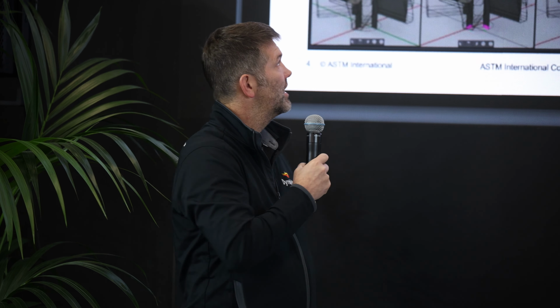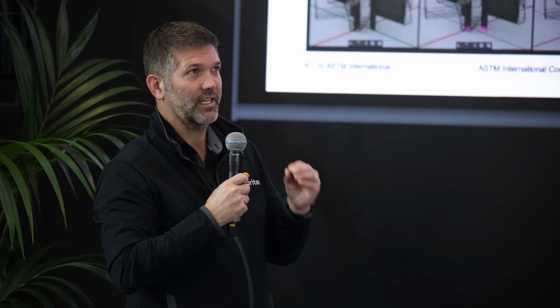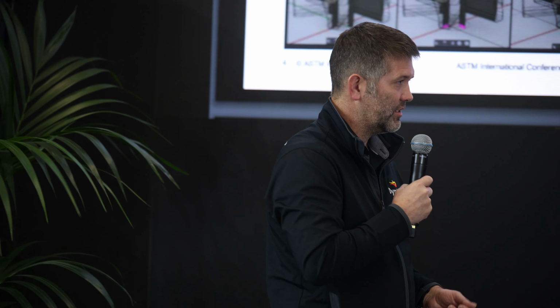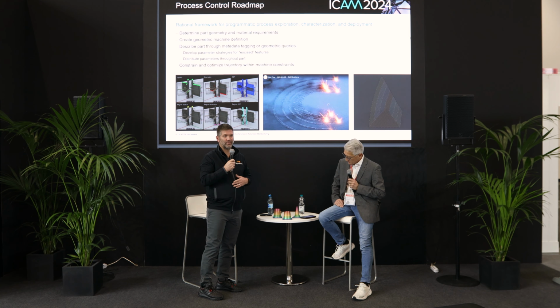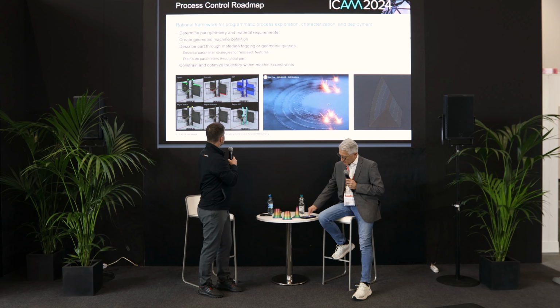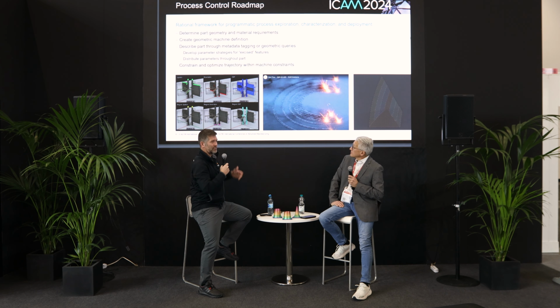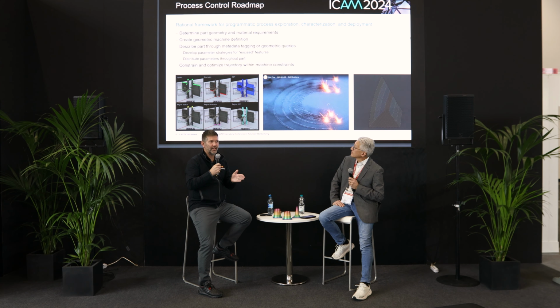We really start with specimens. We all see specimens all over, tensile specimens, feature specimens, and that's what we use to develop the process because it's easy to characterize. It's easy to set up test geometry. We section things. We look at the melt pool. But ultimately we want to put those in a final part. And so the strategy is start with specimens, define your rules, then qualify those rules in the context of qualification, sensitivity analysis to your process, but then use the exact same set of queries in the final part.